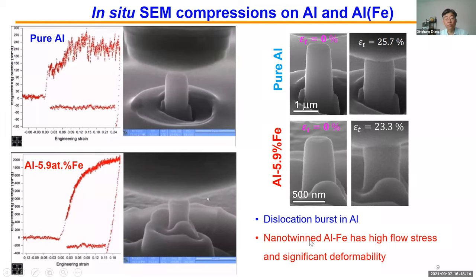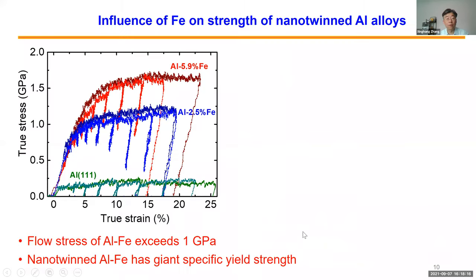Now we call it nanotwin aluminum iron films. In this chart, we're compiling all these aluminum iron films together, with different doping concentrations, 2%, 6%. And you find that, compared to pure aluminum, this is much stronger. You can get 1 GPa under compression, or sometimes 1.5 GPa. So that's very high flow stress. It is already comparable to some of the high-strength steels, but of course in thin film format.